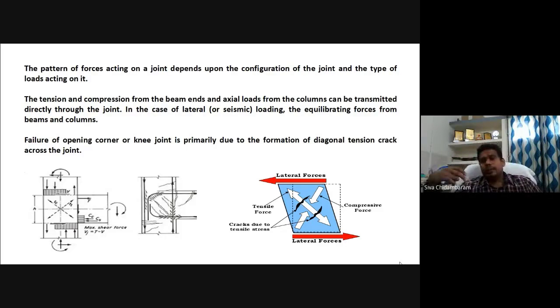Okay. So a crack is generally a good sign in RCC elements. Like a fever to a human body, a crack is a sign that tells you something is happening to the RCC elements. Otherwise, a building can fail in an abrupt way, which is generally not advisable. So a crack is a warning. If you are able to identify the reason for the cracks, then we can easily retain the structures.